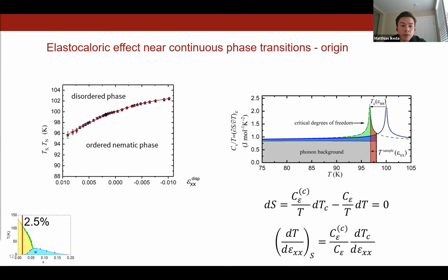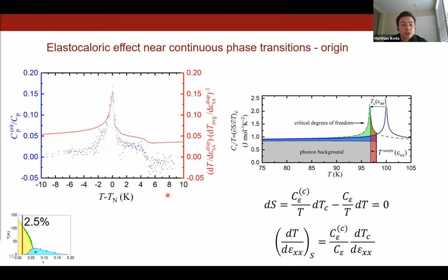out of the sample. And here I would like to show you really quickly just a comparison of elastocaloric effect data, which is shown in red, and heat capacity data, which is shown in blue, just to convince you that indeed both quantities measure a very similar temperature dependence. We can find a feature for the nematic phase transition and a feature for the antiferromagnetic phase transition, here in this case for 2.5% cobalt-doped barium iron arsenide. But I would like you to notice that we indeed measure the elastocaloric effect against very small backgrounds, and the sensitivity of this probe is extremely high.